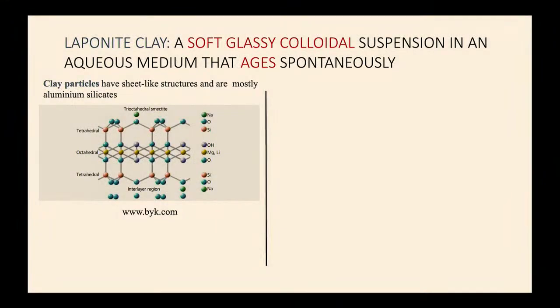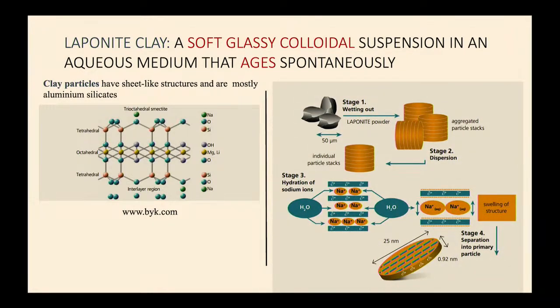So if this is a clay plate, then the faces are negatively charged because of the oxygen ions, and the whole clay particle is surrounded by this Debye layer of positively charged sodium ions. Depending on the pH of the medium, there are these side groups that are magnesium. They get hydrated, so you end up with a disc, a plate, where the faces are negative and the rim of the disc is positive.